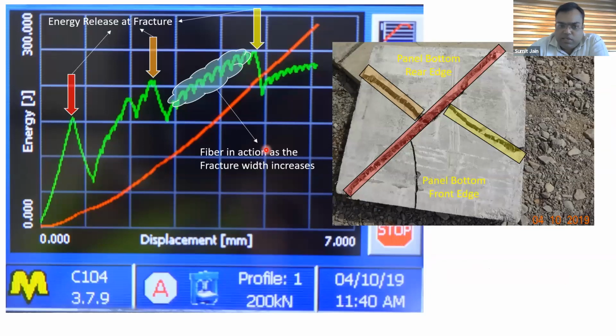Now, on more careful study of the graph, we observed that the 3 peaks and 3 falls in the graph correspond to the cracks. This red peak, where the load went down suddenly, was the first crack which appeared. The orange one reflected this crack, and the yellow one was this one. Initially the load is building up along with the displacement, and the curve is really smooth. There is no waviness in the curve, so we can say that the concrete was taking all the load.